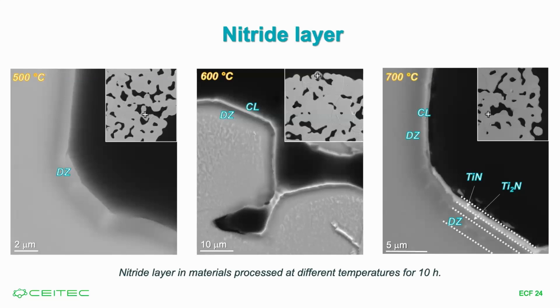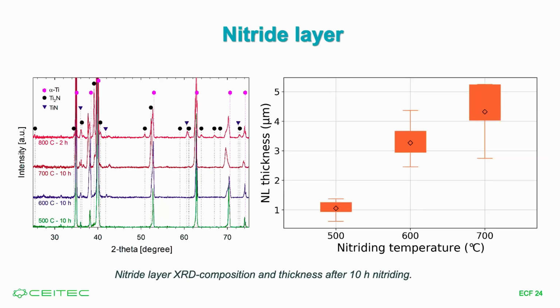So we observed that for these temperatures we tested, 500, 600, and 700 degrees Celsius, we achieved nitridation in all cases. These were nitrided for 10 hours. We don't see compound layer here. We see diffusion zone. The position in the filament is shown here. At 600, we do see some nitriding layer and diffusion zone, and here we clearly see double layer of titanium nitride and titanium 2 nitride. But what we obtained from XRD actually is that these 2 nitrides are present in all 3 samples. They are just not seen, maybe it's very thin. Here is shown how the thickness of nitride layer changes.